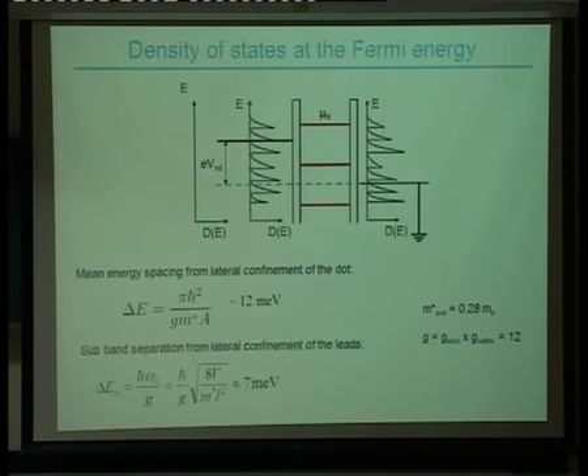You can also imagine what happens to the leads. And I guess one of the key things now is, unlike most quantum dot architectures, where you've got 2-dimensional reservoirs connected to a dot, we've actually got 1-dimensional leads now because they're so thin. So either side, you've got these 1-dimensional density of states in the leads interacting with the quantum dot states. But again, because from the SEM we know the dimensions of the leads, we know that the separation should be around about 7 meV. So you've got these two effects giving you meV energy levels, and yet we're seeing 100 microeV.